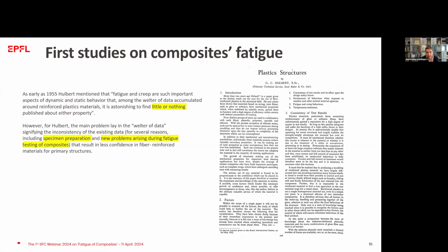1955, where he realized that we have almost nothing published about creep and fatigue. And why was creep introduced so early? Because if you remember, before we discussed this mean stress effect. You can imagine that composite materials have at least viscoelastic behavior at certain ranges of temperatures, or depending on the resins that are used. So we have materials that are viscoelastic. This means that when we have non-zero mean stresses, we have also a component of creep in the fatigue behavior. And this has been identified as a factor affecting the fatigue life of composites, and not metals, already since 1955.